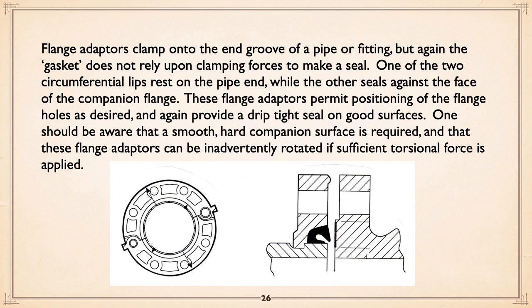The flanges are neat. Flange adapters fit onto the end of your groove pipe. And again, the gasket you can see is sort of almost like a funny C-shaped thing on the sketch on the right. And it seals at the bottom against the outer surface of the pipe between the groove and the end of the pipe, and seals up against the flange that's coming towards it that you want it to go to. These flanges permit positioning of the flange holes as desired. You can rotate it as you want. And again, done properly, a drip-tight seal. One should be aware that a smooth, hard companion surface is required. In other words, where it contacts the fitting or valve or whatever it's going up against, that needs to be in reasonably good shape. Another thing with these flange adapters, though they do have little teeth, give them enough torsional force and they can actually twist.